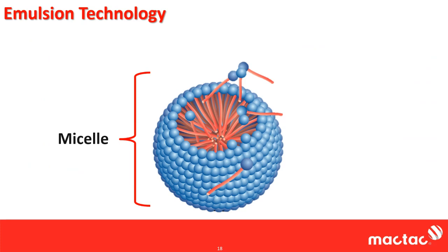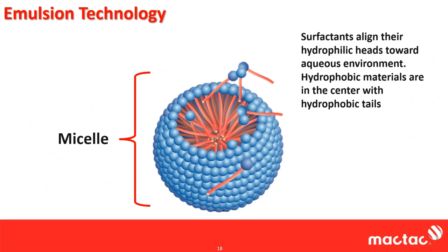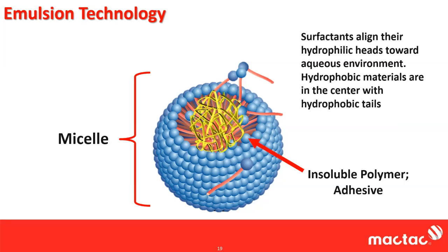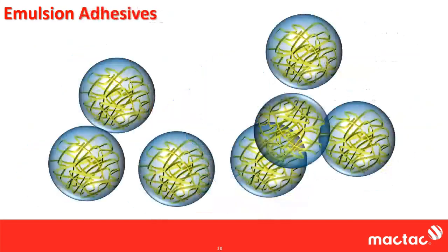Now, this is some detail here, but basically they form these big clumps, these big molecules, we call them colloids. This is the same principle as milk. And what we see here is, again, the heads are aligning out because it's an aqueous environment. The tails are lining in, and that's where the polymer is being made. If we were talking dish soap, that yellow thing that's spinning in there, which I have representative of the adhesive polymer, would be bacon grease or fat or something like that. For laundry detergent, that would be your dirt and your grime. In this case, it's polymer, and this is how emulsions work. You need these surfactants. You get all the insolubles encapsulated in a surfactant, and then that's where the actual polymerization occurs. So again, I'm talking about this because this is the basis of the technology.